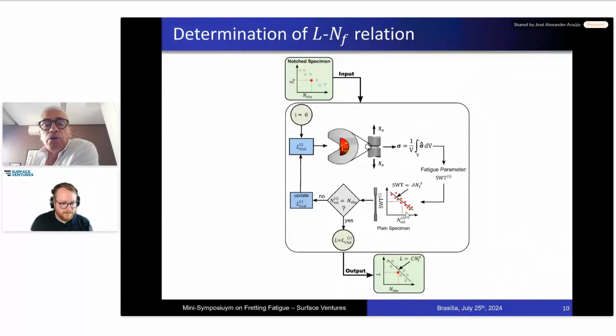In parallel, we will be running tests with plain wires, without any type of notch. And then with this second set of tests, we can develop a Smith-Watson-Topper against life relation. And then now I can get the Smith-Watson-Topper computed in this process zone, enter with it in this SWT against N curve, and then I obtain the estimated life.